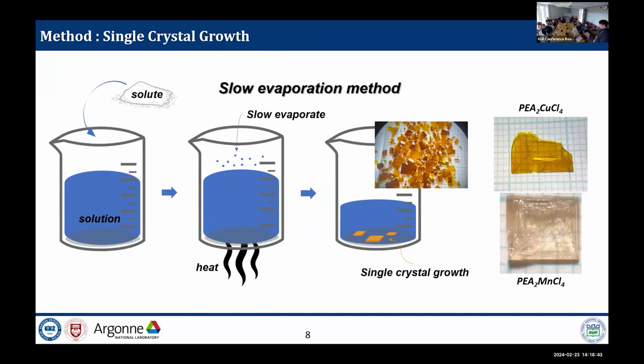So now let's move to the experimental part. We made these PEA-based organic-inorganic hybrid perovskites, PEA2 copper tetrachloride and PEA2 manganese tetrachloride, using the slow evaporation method. This method is very simple. Just choose a solvent and solute, dissolve the solute in the solvent, and heat the solution. Then it will slowly evaporate, and the dissolved material will precipitate or nucleate and grow into a crystal. We chose methanol and isopropyl alcohol as solvent, and copper chloride dihydrate, manganese dichloride tetrahydrate and phenethylamine hydrochloride as solutes.